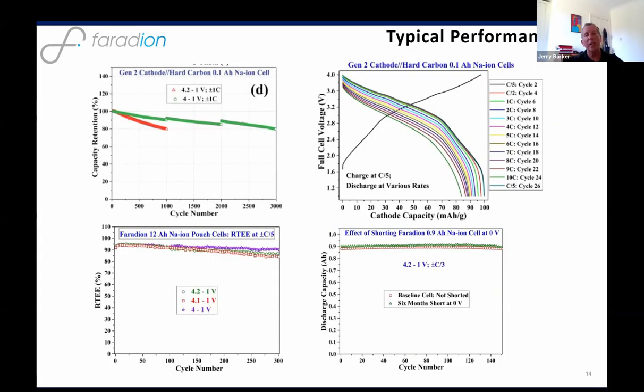Cycle life, if we do 80% depth of discharge, gets out to 3,000 cycles. Rate performance I've not mentioned, but we can go up to 10C discharge. Round trip efficiency is an important one for a lot of applications. It generally runs close to 95% depending on the rate. And I've mentioned the 0 volt capability. That's data up to 6 months.